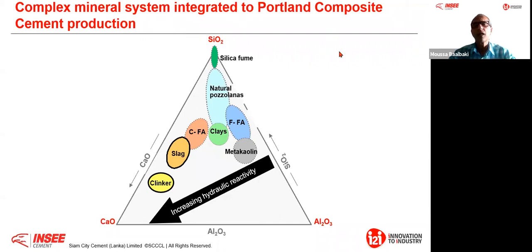Now I would like to talk a little bit more in depth about Portland composite cement production. It has what I call a complex mineral system. What is this complex mineral system? When I look at all the ingredients that are used today in our 4 cement standards, they are all within this ternary chemical composition of calcium, silicate, and aluminate. You see you have clinker and slag on the left side. This is why we say slag is latent hydraulic: slag has a basicity of 1 or more than 1, therefore slag by itself can react with water.